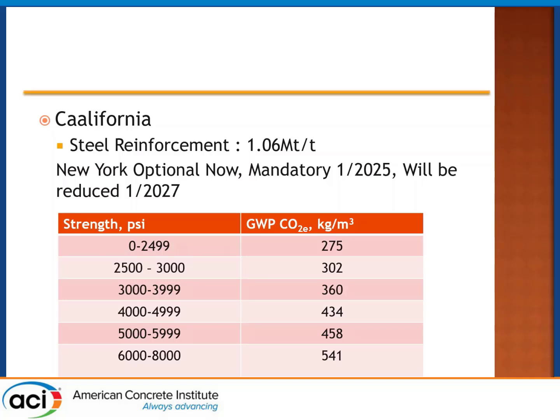And so they have listed the compressive strengths, including the very accurate 4,999 PSI, which we are all laughing at now, but since the difference between 4,999 and 5,000 is what, 24 kilograms per cubic meter? You can be sure that there will be a lot of 4,999 PSI specified. And you can see that it's going to happen, right? Because we're all going to try to solve our problem. And so you can see we're allowed to emit for low-strength concrete as much as 275 kilograms per cubic meter.